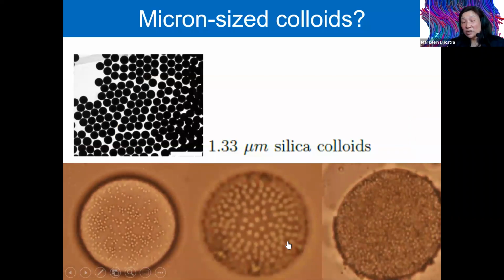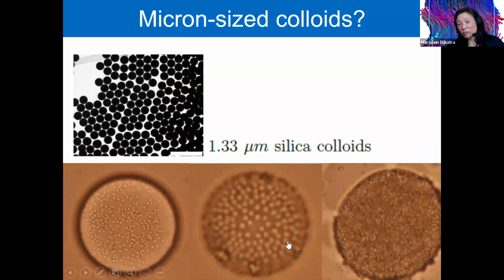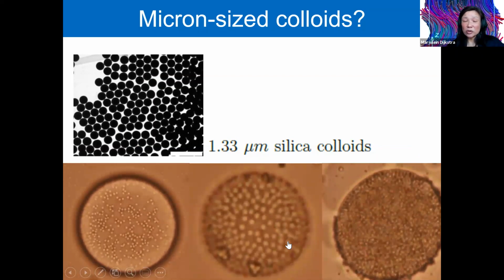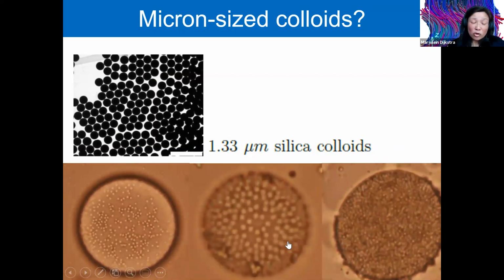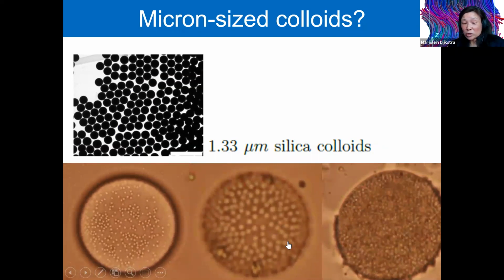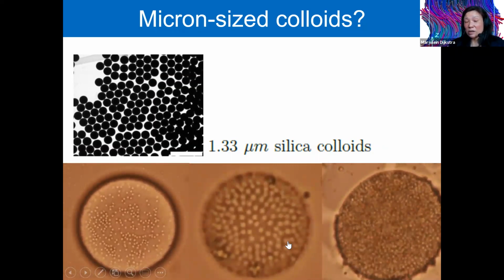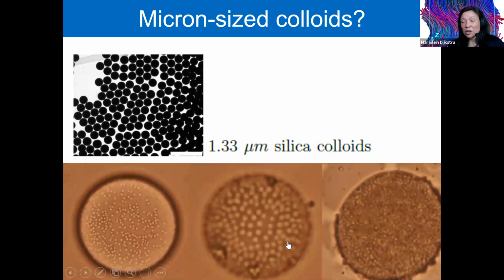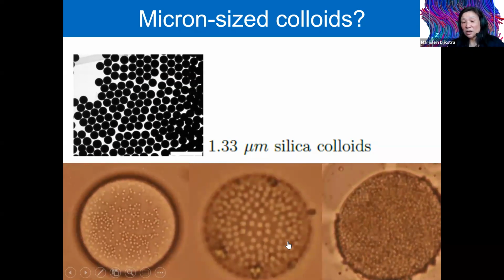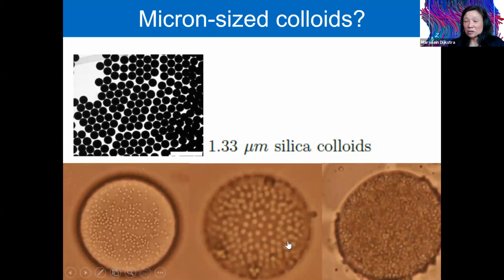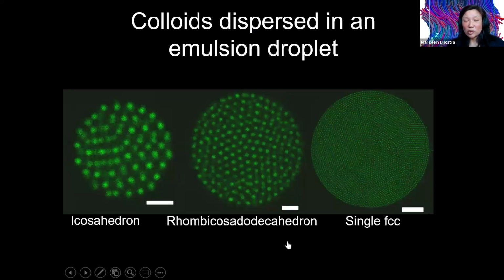One can also do the same trick with bigger colloids. These are 1.3 micron sized silica colloids. One can clearly see the colloidal particles in these emulsion droplets, and by just evaporating slowly the solvent out of these emulsion droplets, one can increase the density in such a way that it self-assembles into these beautiful icosahedral structures, or rhombicosidodecahedral structures, or these single FCC. So also for the bigger colloids, we find all these beautiful structures just by putting spheres inside a sphere.